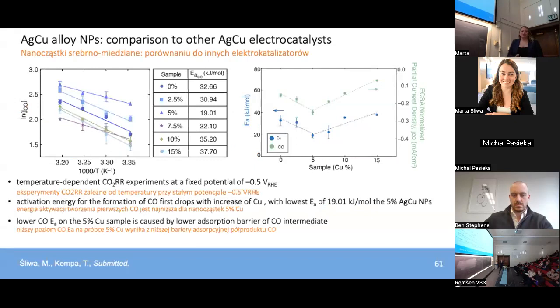To better understand the CO2 reduction process that's occurring on the surface of those silver copper particles, we also performed temperature-dependent CO2 reduction reactions at a fixed potential of -0.5 volts. A plot of the partial current density for the carbon monoxide product versus the inverse of the temperature gives us a slope which corresponds to the activation energy for the formation of the carbon monoxide. And if we plot that activation energy in relationship to the percent copper that we introduce into these alloys, we see a very obvious dip with the lowest activation energy for that carbon monoxide product occurring for the 5% copper sample. So it's likely that this lower activation energy is due to some electronic effects occurring between the silver and copper in these alloy nanoparticles that stabilizes that CO in just the right way to propel its formation as the major product.